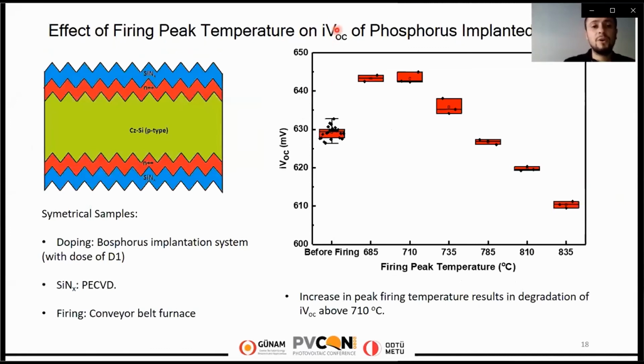Before cell fabrication, we also investigate the effect of firing temperature on the implied Voc of phosphorus implanted wafers. For this, we fabricated symmetrical samples, as you see in the figure here.